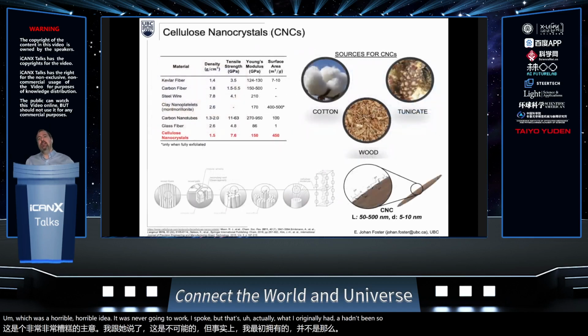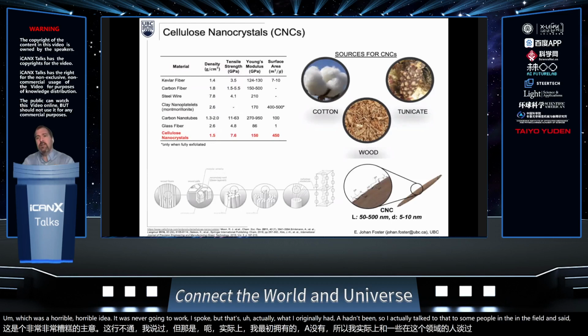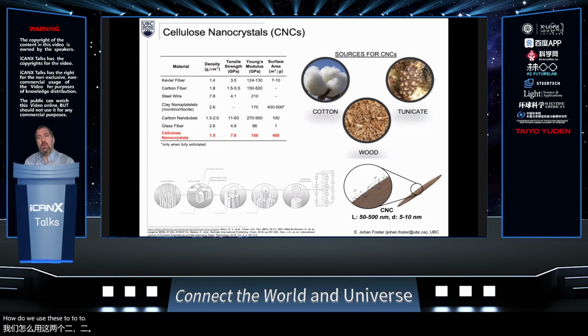So I talked to some people in the field and said, "Hey, here's my wonderful cellulose nanocrystals. How do we use these to reinforce metals?" And they said, "Well, there's some obvious problems here. The stiffness of your material is good, but not compared to metals. And the other problem is the thermal stability is off by an order of magnitude. So our cellulose nanocrystals start to degrade at about 150, 180 degrees. And any of these titanium alloys, we're going to start to sinter at 1,000 or 1,200 degrees. So problematic."